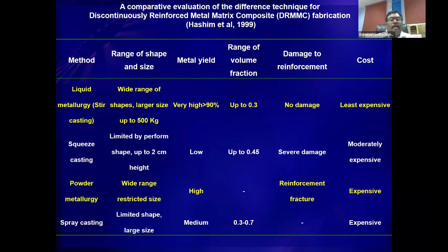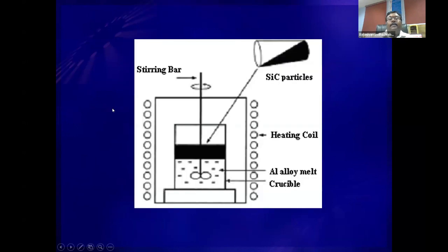And among the associated technologies of liquid state processing, we have squeeze casting. In squeeze casting, we can go up to 45% volume fraction. That means as a fraction it is 0.45, in terms of percentage 45. But sometimes you have some damage to the fiber or particle because pressure is applied, and it is also moderately expensive. And powder metallurgy, compared to liquid metallurgy, is highly expensive. So for commercial production and mass production, it would be possible to take up the stir casting technology.